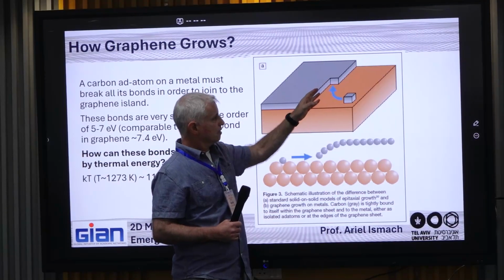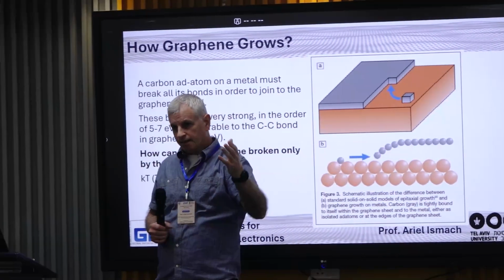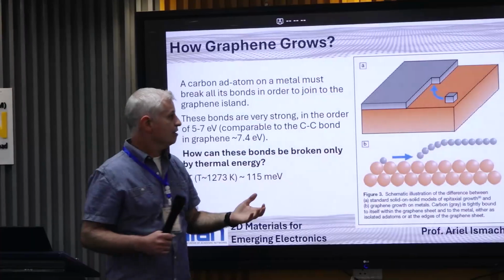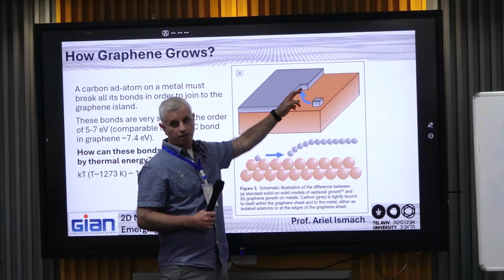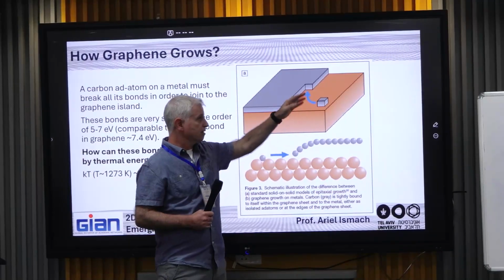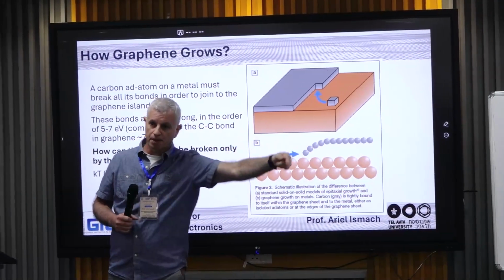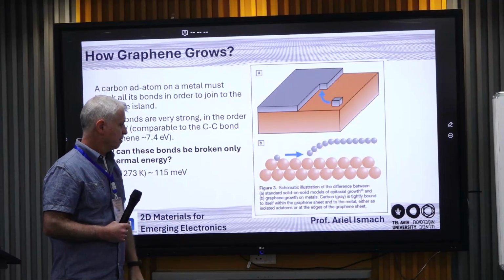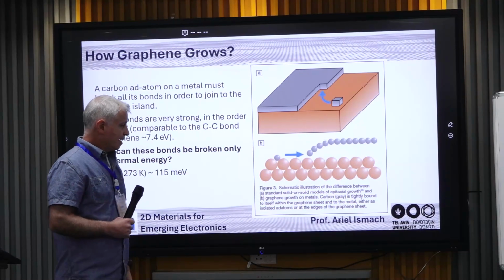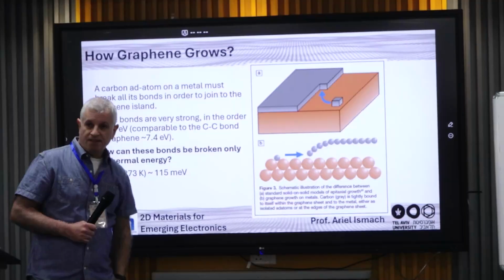And when you have a new atom on the surface, it will diffuse on the surface till it reaches the preferred site, which is in this case the kink. And the energy that it needs to pay for the incorporation is not high. It's just the energy of hopping from site to site, similar to what we saw before. But in the case of graphene, it's extremely different.